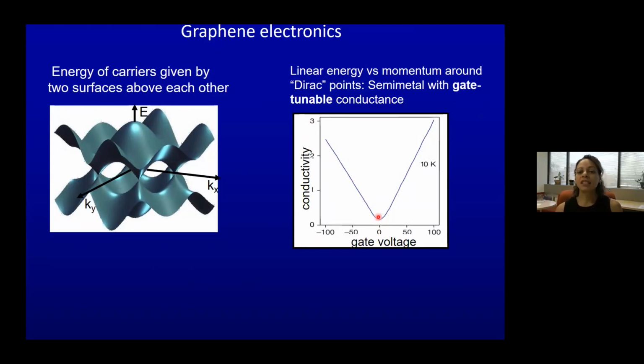So graphene is a semi-metal. Its conductance doesn't go to zero when you apply a gate voltage, but it does go to a minimum. The conductance isn't pinched off entirely like a semiconductor. It's not flat, but it goes to a minimum and then rises on either side. So you get a minimum conductivity with a linear conductivity around it. So it's a semi-metal with a gate tunable conductance.